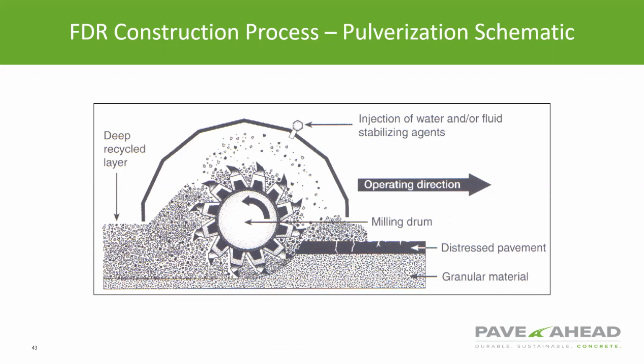Here's a good representation of what's happening inside that drum. It's moving to the right side of the screen, and you can see the operating direction there, so it's doing an upcut method. A lot of the drums have hydraulic rams on them to keep them down, so the front part of your skirt becomes pressure against the asphalt to keep it from slabbing up on you so you can get your gradation. But you have to take into account speed and your drum door openings to get the best gradation possible.